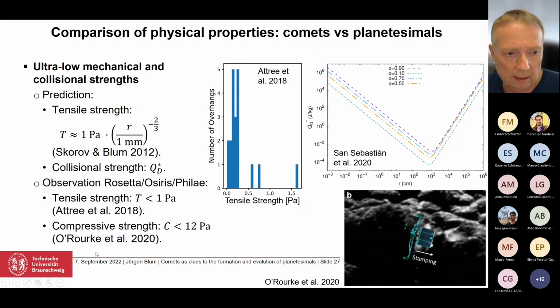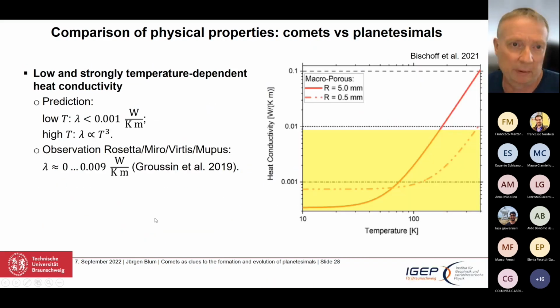More recently, Larry O'Rourke and colleagues in 2020, by analyzing one of the Philae impacts, the unsuccessful landing attempts on the cometary surface, measured the compressive strength to be less than 12 Pascal. We don't have a model for that yet, so there's nothing to compare with. And the collisional strength, another number, has been modeled by San Sebastián et al. 2020. It is also an extremely small number, orders of magnitude smaller than for the classical model of a makeup of a planetesimal. So that's, again, very strong indication of 67P being a pebble pile.